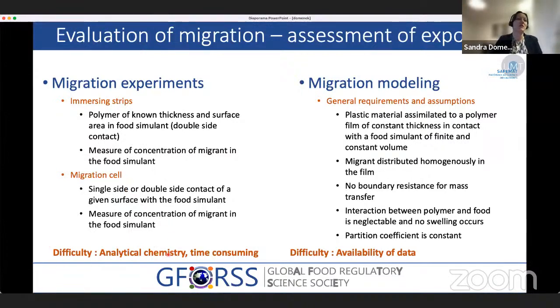The difficulty here is linked to the analytical chemistry, because you will need very low limits of detection and very specific materials for analytical devices in order to detect your contaminants. And it is quite time consuming. The legislation does also allow migration modeling, and this is quite good news because, as I told you before, the physical chemical background is very well known, which means that the migration can be calculated. It can be calculated especially when you know the different transport parameters of your system and when the interaction between the polymer and the food is negligible, which means that your transport is following Fick's second law. Here, the difficulty is, of course, the availability of the data of the transport properties.